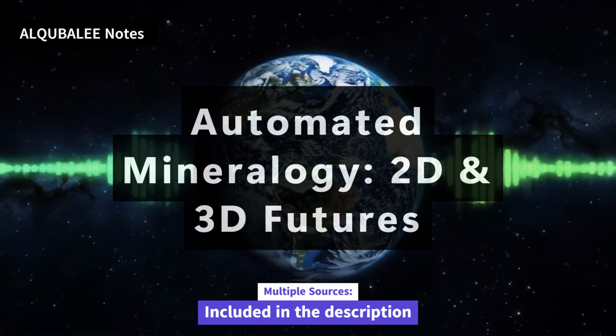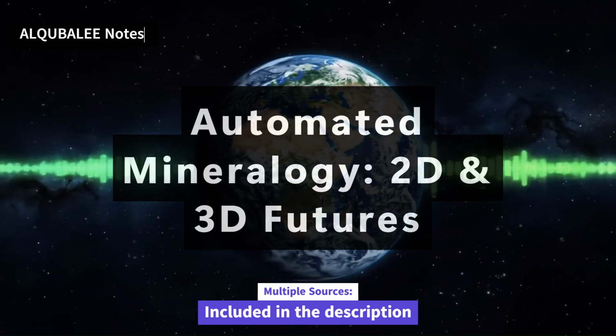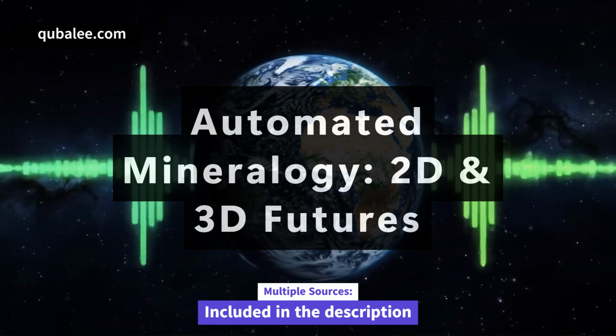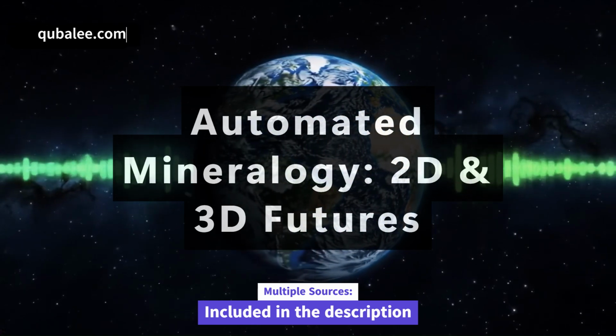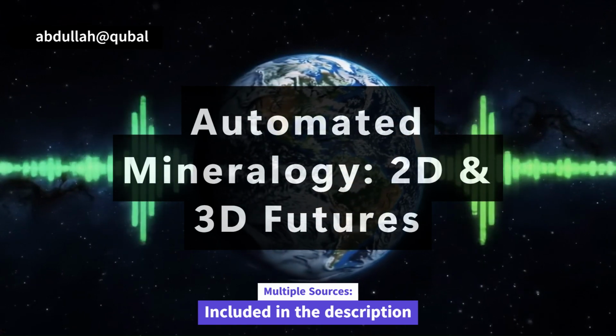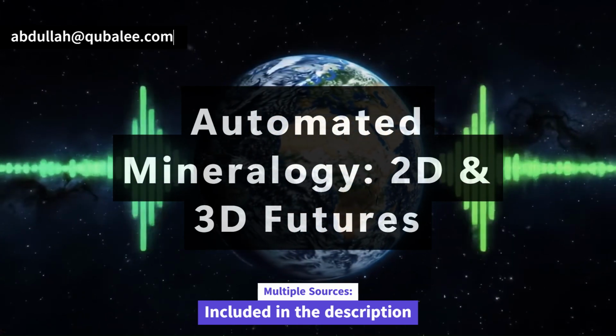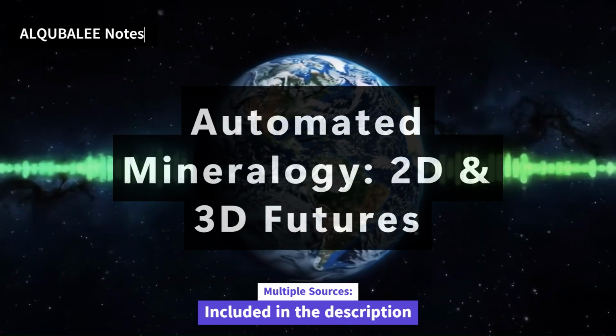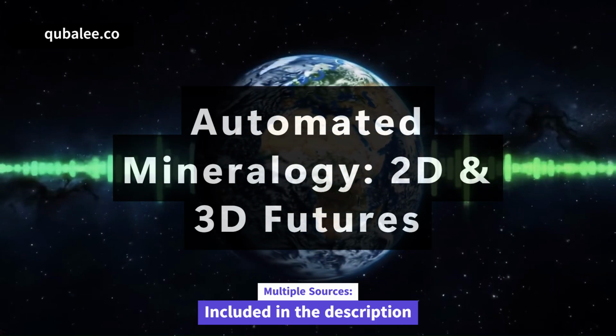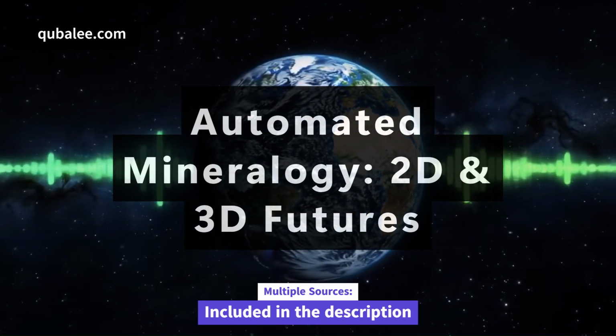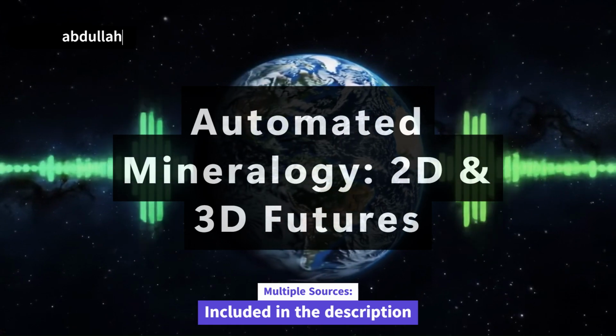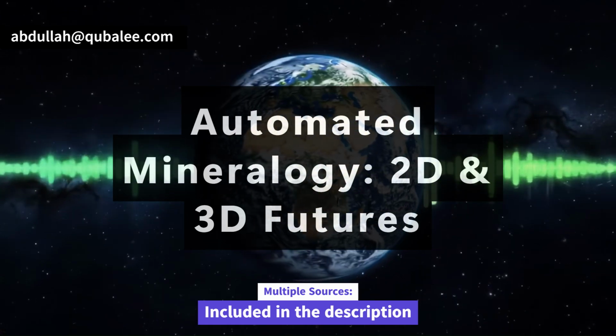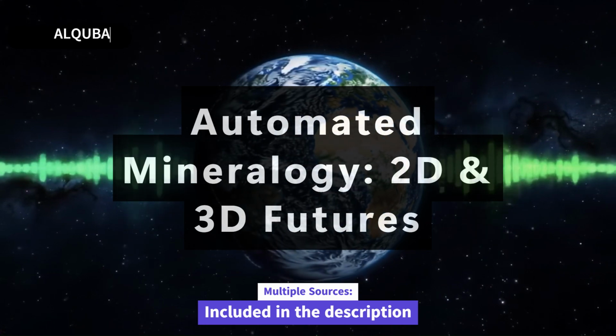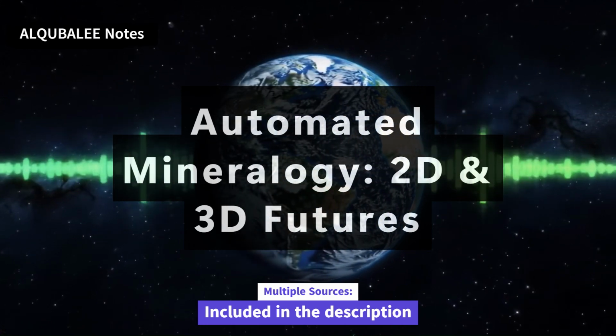And what did that reveal about the cobalt in pyrite? It was fascinating. This high accuracy, low-level quantification showed that the cobalt wasn't just evenly spread through the pyrite grains, as you might assume. It was often highly zoned, concentrated in specific bands or patches within the pyrite crystal. Wow. That kind of detailed spatial information about trace element distribution is critical for understanding how ores form or how those elements might behave during mineral processing. It's a level of detail you just couldn't get easily before. That's a fantastic example of going beyond just ID.